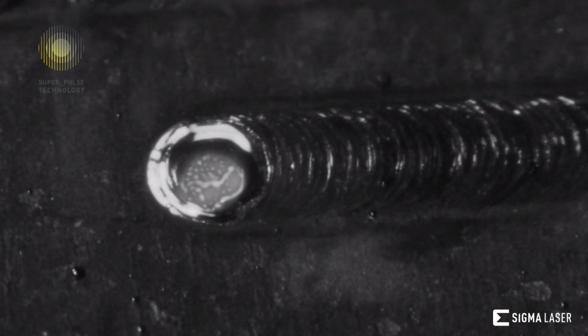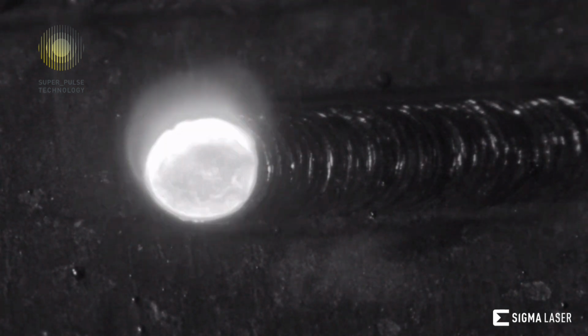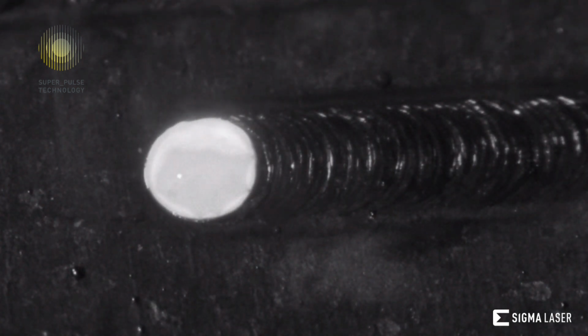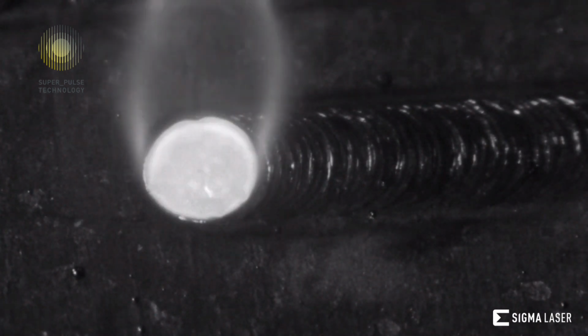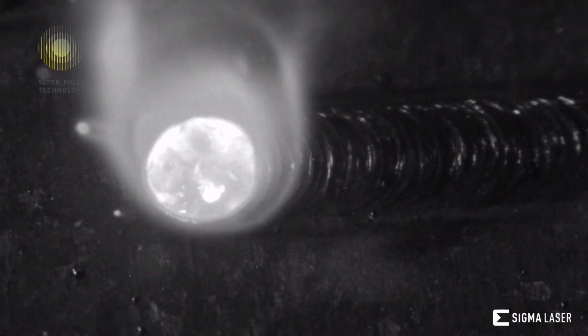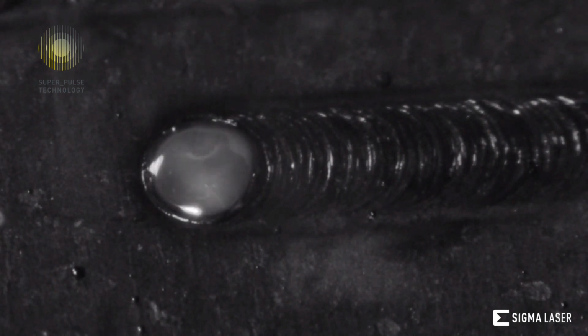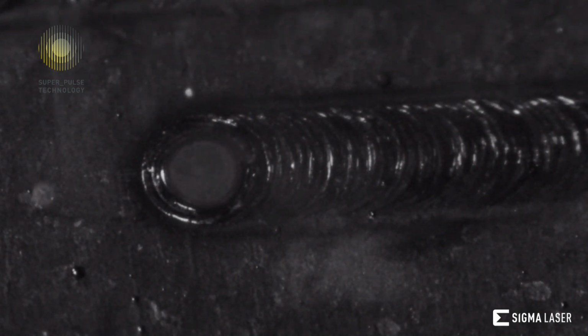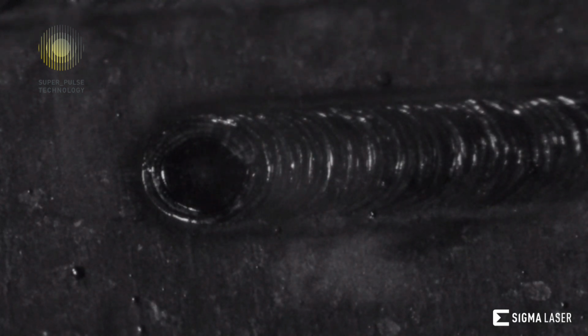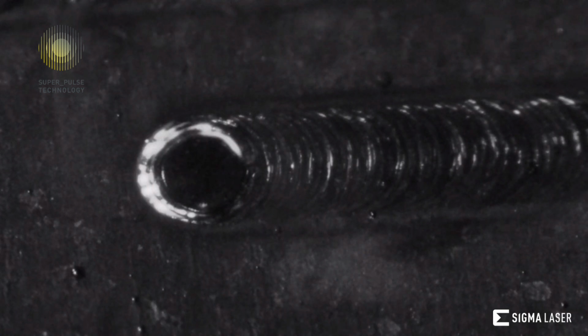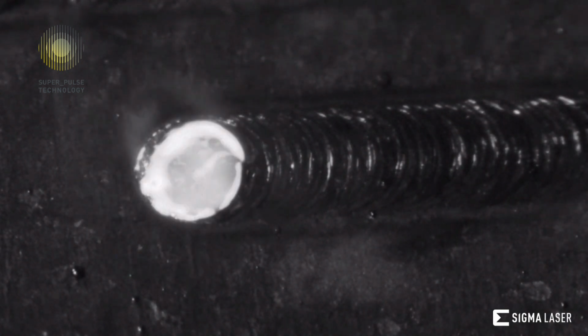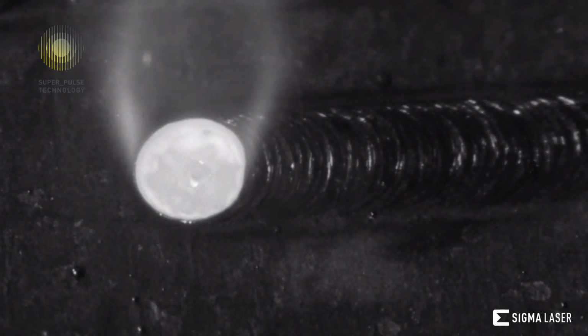In comparison, a completely different behavior becomes visible. The molten pool remains calm and stable. No turbulence, no boiling. Energy is not released uncontrollably, it is guided. The T8 to 5 time remains within a defined optimal range. Stresses are prevented before they can lead to cracks. With controlled energy, the molten pool remains stable and cracks are prevented. What becomes visible here changes industrial practice.